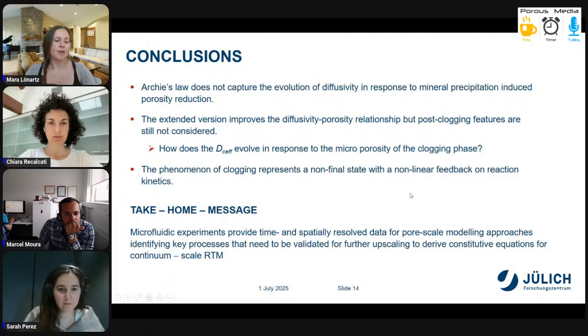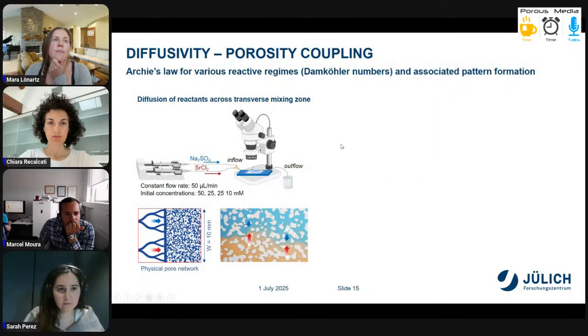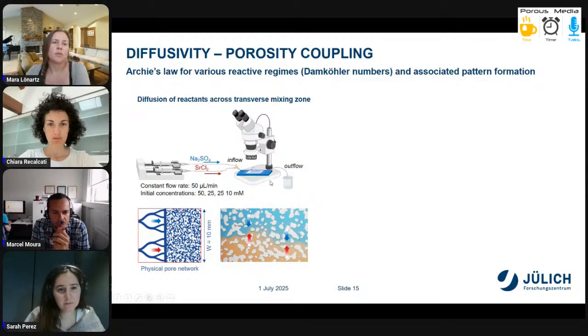Just to give you a short insight into my second project, that was more focused on the variations in the reactive regimes, so assessing the effect of the Damköhler number on the porosity-diffusivity relationship. For this, I used a slightly different setup, so it was also conducted with a microfluidic chip, which